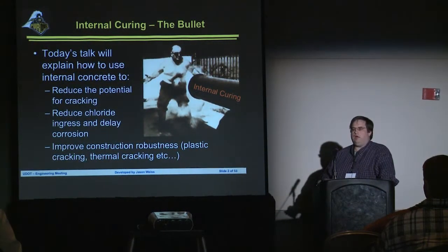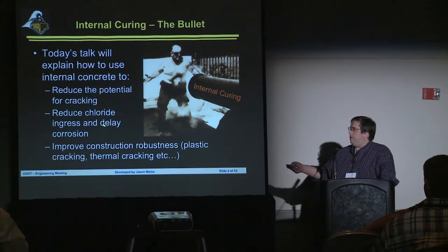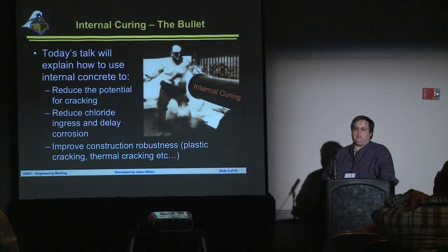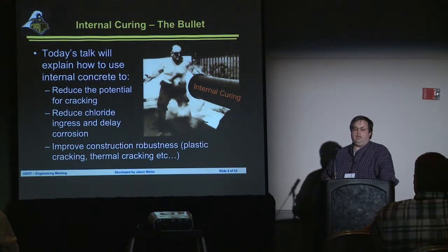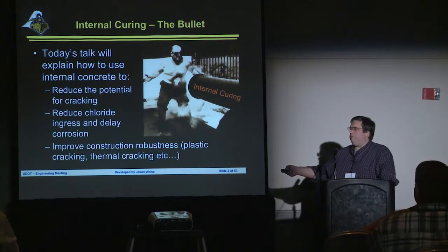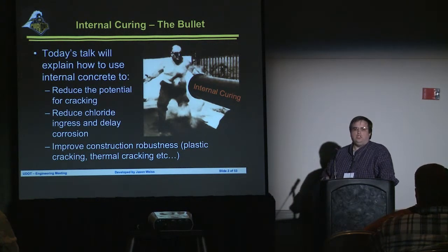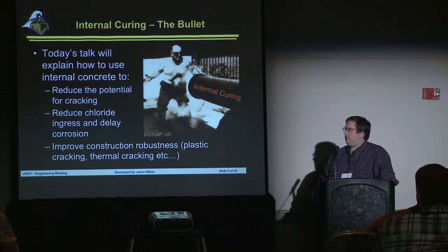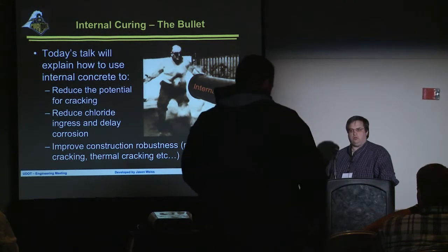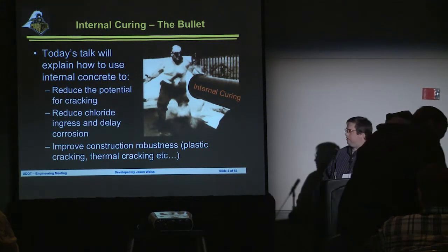We're also going to try to reduce the ingress of chloride ions. We know we use a lot of chlorides to keep our roads free of ice. So by internal curing, we're going to be able to reduce how fast these chlorides get in and delay the rate of corrosion of our reinforcing steel. And then we also have a benefit of improved construction robustness. So all of a sudden we're not as susceptible to slight changes in temperature, to improper curing technologies, or to a dry, windy day when things are cast. These are the three things that internal curing is going to give us. So this is the answer. And what I'm going to do is talk for the next 45 minutes or so about how we got to this point and how we manufacture internally cured concretes, and show you some data that backs this information up.